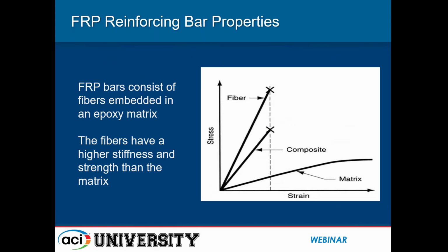So if we take a look at FRP reinforcing bar properties, we see that they're different from a traditional steel reinforcing bar. Steel has a linear elastic response up until the point where it yields or begins to deform under the same load with continued deformation. We see that the fibers of the GFRP do not yield. They are linear elastic up until failure.